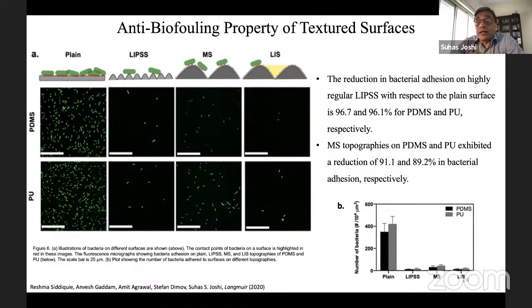Anti-biofouling properties were tested by putting bacteria on the surfaces: plain surfaces, LIPSS surfaces, multi-scale surfaces, and the liquid infused multi-scale surfaces. If you provide some kind of liquid in the cavities along the surfaces, their anti-biofouling properties increase, and they can be extended over a longer period of time. You can see that for the replicated structures, PDMS and PU, the number of bacteria retained after a certain period of time is much smaller, comparatively much smaller. So the multi-scale structures offer significant anti-biofouling properties.